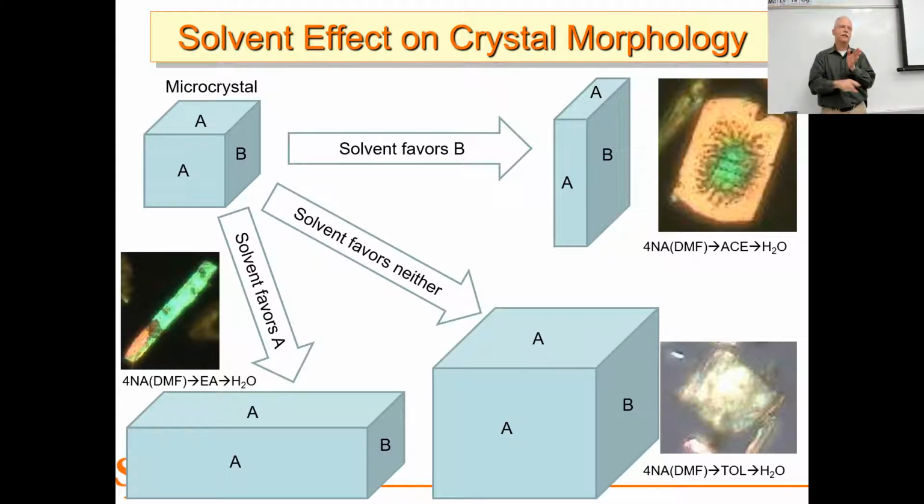If you look up there, the A faces have, let's say in nitroaniline, those are the ring faces, or the edge of the ring. And so you might have those faces be similar all the way around, but then the end faces have amine groups and nitro groups. Maybe they alternate because they're going to line up with the polar dipole moments. You've got nitro and amine, all on face B. And at the other end of the molecule, you have nitro and amine. So the B faces are different than the A faces. You follow me? And this is going to be very similar in many, many crystals.